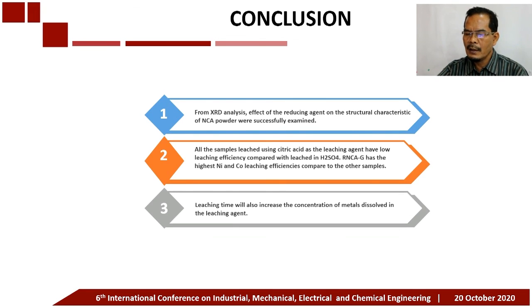From the XRD analysis, the effect of the reducing agent on the structural characteristics of NCA powder was successfully examined, with the result that glucose is the best reducing agent for the pretreatment of spent lithium-ion batteries. The second conclusion was that all the samples leached using citric acid as the leaching agent have low leaching efficiency compared to leaching using sulfuric acid.